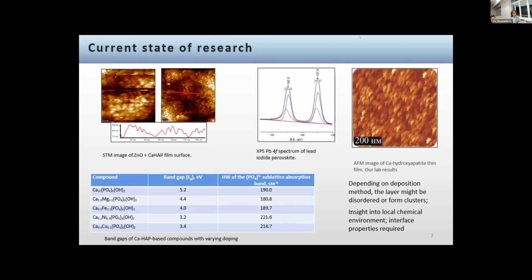But as you can see on this picture, and also on the right-hand side picture, these films of the apatite layer cannot necessarily have a perfect crystal structure. Their structure actually depends on the deposition method, especially in case of magnetron sputtering deposition. There might be some disorder, some important disorder even, or some nanoclusters forming.